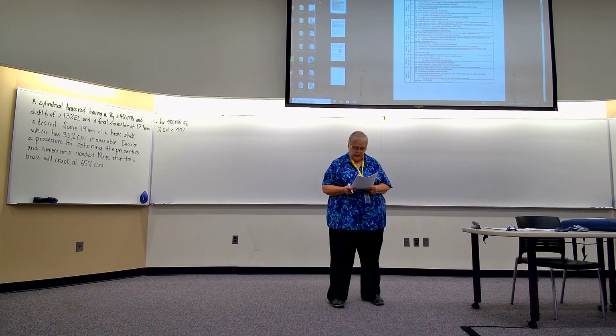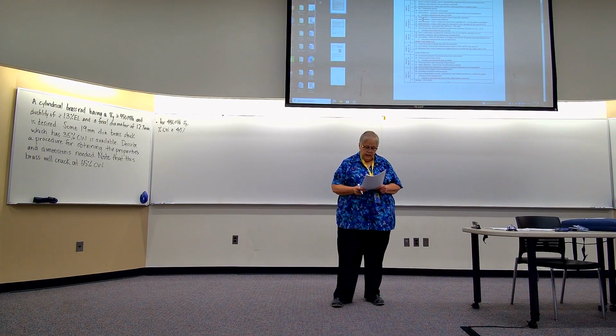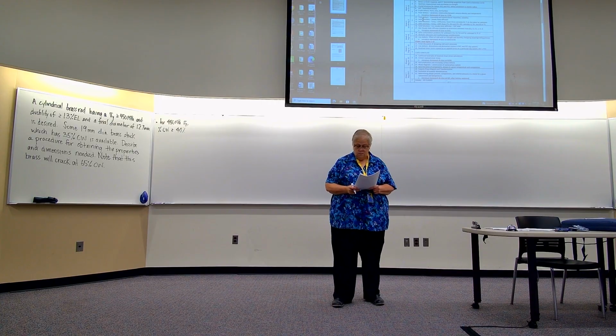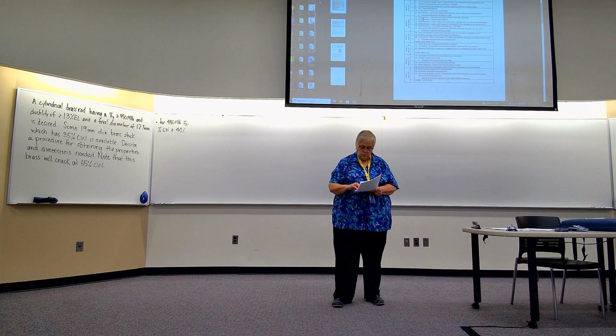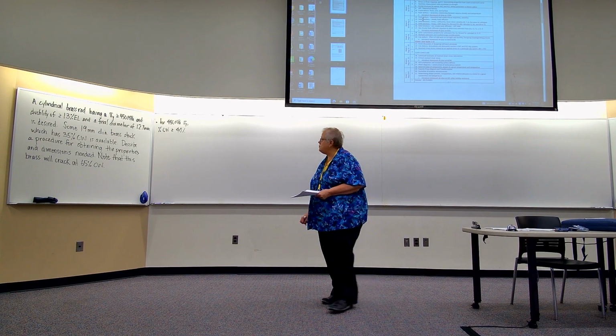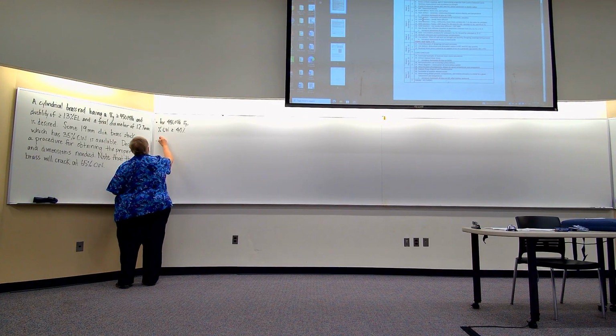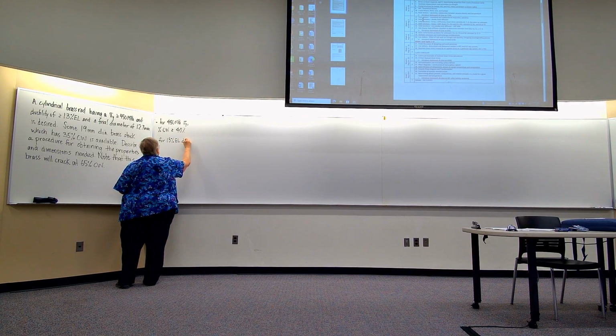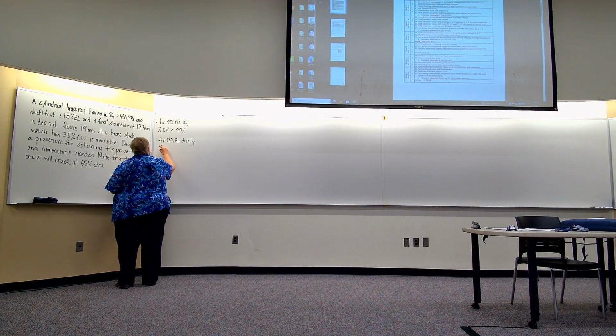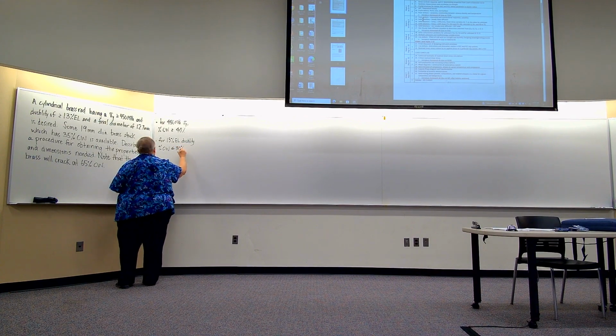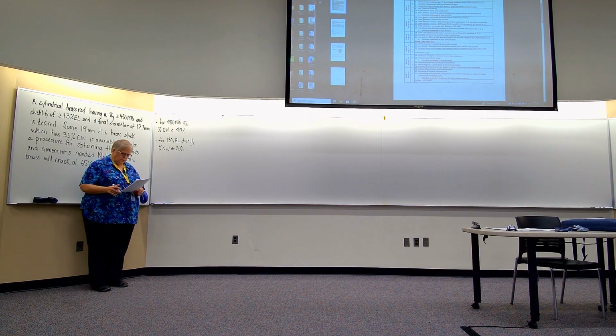I want 13% ductility. So that looks to me like pretty close to 30% cold work. So that means that the percent cold work has to be less than or equal to 30%. Wait, that's getting impossible. Brass, 13, 30%. Strength, 450, 40%. Okay, I know they didn't intend for this to be an impossible problem.